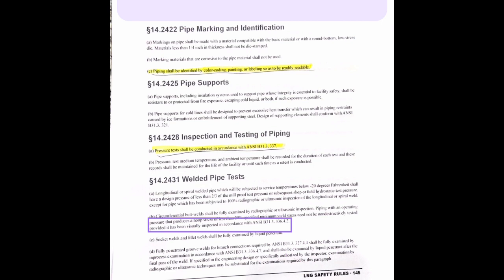C. Socket welds and fillet welds shall be fully examined by liquid penetrant. D. Fully penetrated groove welds for branch connections required by ANSI B31.3, 327.4.4 shall be fully examined by in-process examination in accordance with ANSI B31.3, 336.4.7 and shall also be examined by liquid penetrant after the final pass of the weld. If specified in the engineering design or specifically authorized by the inspector, examination by radiographic or ultrasonic techniques may be substituted for the examinations required by this paragraph.